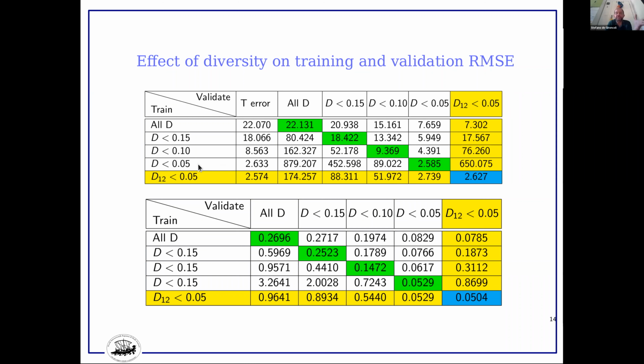So if you look at all configurations that are very similar to diamond, you can get a training error which is very small. 2.6 meV per atom is a very small number. And if you look at the validation data set of the same type, similarly very close to diamond, the validation error that you obtain is also very, very small. So in this sense, you would say, okay, I can have a very good error if I concentrate on diamond. Yes, but only if you are interested in structures that are very close to diamond. Because if you then look at the validation error for structures that are farther and farther from diamond, you obtain errors that are a complete disaster.